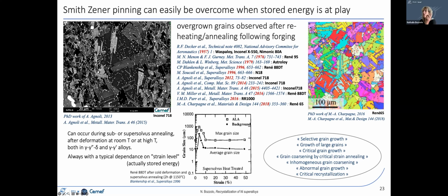In all these cases, the common feature was that you have initially stored energy in the microstructure. And actually the reason for which these grains could grow despite the Smith-Zener pinning pressure is that the driving force which makes the boundary migrate is a combination of capillarity forces and stored energy. And the stored energy term is very easily large enough to overcome the pinning pressure. Therefore, these phenomena have a very clear dependence on the strain level, actually the stored energy level you have initially in the microstructure, with a clear dependence of the maximum grain size you would get on the stored energy level.